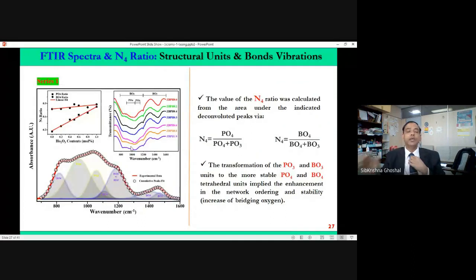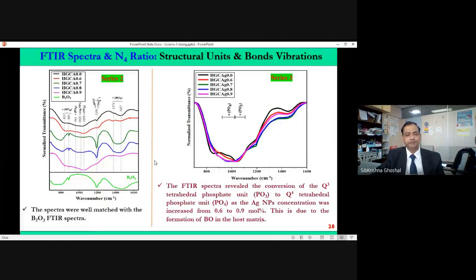How do we check? We call something called N4 ratio. N4 ratio means to show that PO4 units are more in the system, BO4 units are more in the system than other units. And that clearly indicates that yes, indeed, they are there. So we are making the glass ceramics which are highly stable. So this one issue is solved.